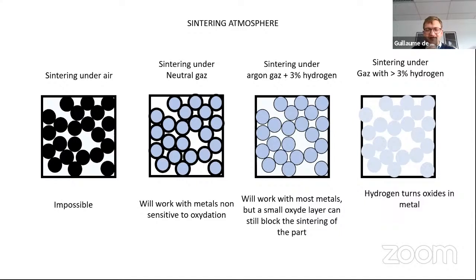Let's talk a bit about sintering atmosphere. When we sinter metal, we need furnaces that will be put under neutral gas, protected atmosphere, for a very simple, understandable reason. If you sinter it under air, very quickly, the metal is going to oxidize. And instead of having a metal powder, you're going to have an oxide powder, and you won't be able to sinter anymore. So there are three options usually on the market: sintering under neutral gas, sintering under argon plus a bit of hydrogen, or sintering with pure hydrogen. And this will really depend on the material you're sintering. Some metals are very non-sensitive to oxidation, and you can sinter them under any neutral gas atmosphere.